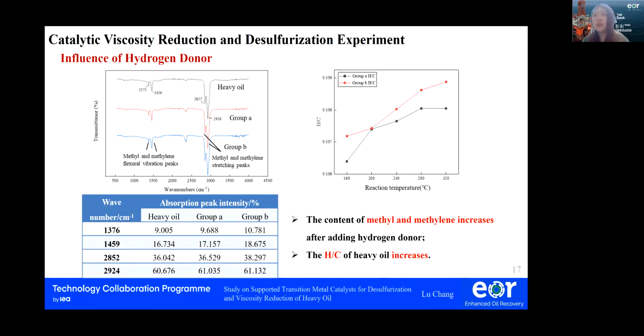The peak intensities are shown in the following table. And it can be found that the absorption peak intensity of methyl and methylene groups increases, which means their contents increase after addition of hydrogen donor. And the picture on the right-hand side is the element analysis of oil samples. And it can be found that the hydrogen-carbon ratio increases after the hydrogen donor is added.